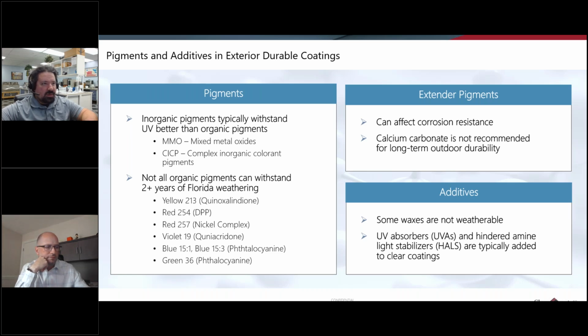And then this, back to what I was saying about don't put in anything that is going to act as a bad actor. Inorganic pigments are a lot better than organic pigments in general when it comes to durability. I don't have to go through all these. Extender pigments, those don't usually have that much of an effect. By extender pigments, I'm talking about mineral fillers. Those can improve corrosion resistance and scuff resistance and some different properties, but they don't usually have much of an effect on UV, except calcium carbonate's not the greatest. That's usually used for more low cost or interior applications.